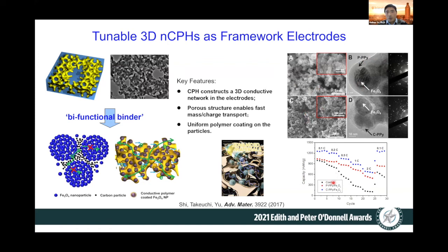So by comparison with the conventional method to make it, these are synthetically tunable conducting polymer hydrogels. So you can see under different C rates, 2C means 30 minutes charging, 0.1C means 10-hour charging and discharging. So you can see this magnetite particle can work with a very minimum amount of conducting polymer gel, about 10 to 15 weight%. So the control, you actually need over 40%, but still at a higher rate, they have very small capacity you can utilize.